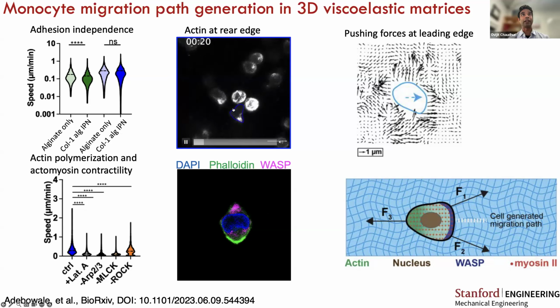If we look at the actin cytoskeleton dynamics, what we see is that there's dense puncta of actin at the very rear of the migrating monocytes. And if we do some stainings, we see that opposite of that dense actin puncta, we see WASP. And then finally, if we do some traction strain microscopy experiments, looking at how the matrix is deformed around these migrating monocytes, we see that ahead of the leading edge, there's evidence that the monocytes are pushing in front of the leading edge.